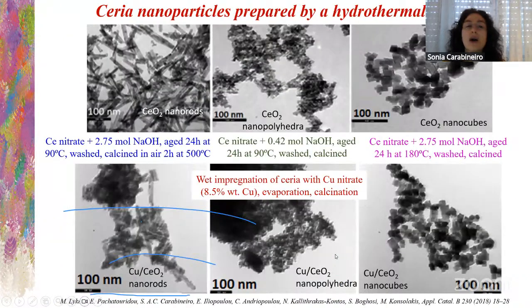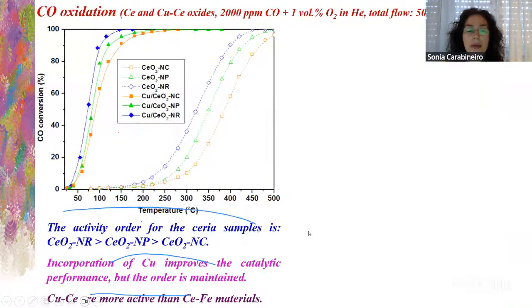We have here also ceria nanoparticles prepared via hydrothermal method. So the same ceria nanoparticles, but this time they were impregnated with copper nitrate. So we have copper on ceria nanoparticles. Here we have the activity: nanorods are better than nanopolyhedra than nanocubes, so very similar. The incorporation of copper improves the performance as expected, and copper ceria are more active than the iron ceria material. So that's interesting to know.